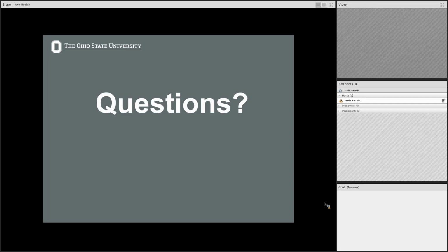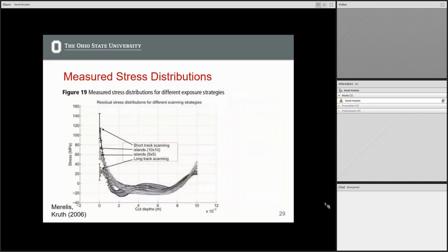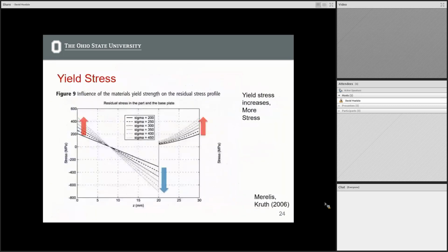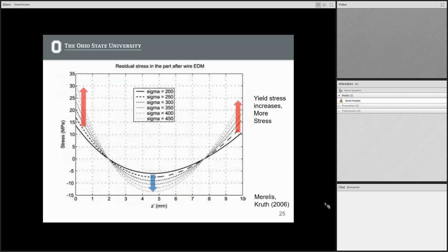Yeah. So you mentioned that this analysis was run for 316 stainless, but then they also kind of discussed what would change results for materials. Is there anything interesting or notable from the material? So that was taking a look at, theoretically, the yield stress. Okay. Let me go back here. Yeah, so the main thing is that as you increase the yield stress of the material, you're going to begin to build up more and more residual stresses in your parts. And that's both in your process to print it, as well as your part once you remove it from the build plate, based on their theoretical model.